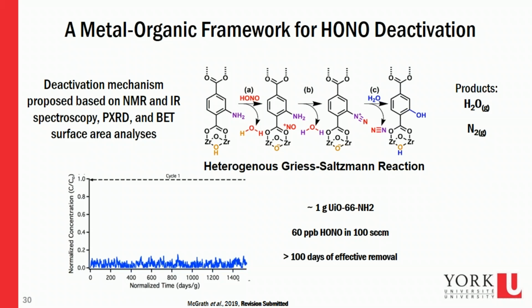We've gone further with this and actually figured out what the mechanism is. So this is what we originally designed the metal organic framework for, is to perform this heterogeneous Griess-Saltzman reaction. So anybody who knows about the LOPAP for measuring HONO or for measuring nitrite by chemical derivatization, you convert it to a diazonium dye. Basically, we're doing the same thing, except now we're doing it heterogeneously. So you take HONO from the gas phase, we react it on the surface of the metal organic framework that's functionalized with this amine group.